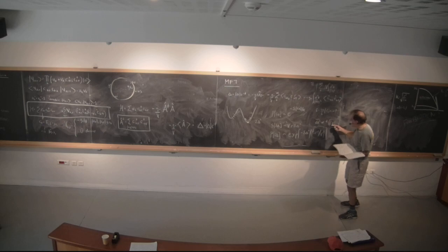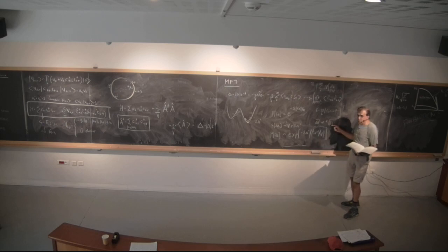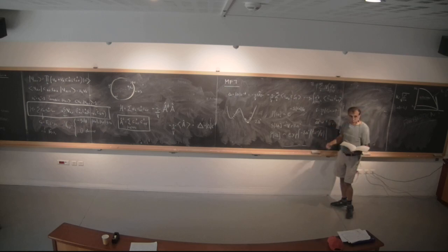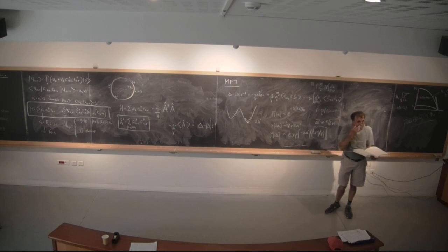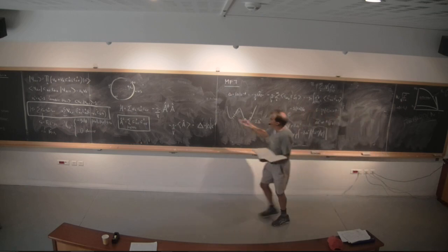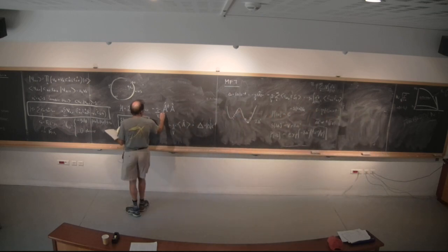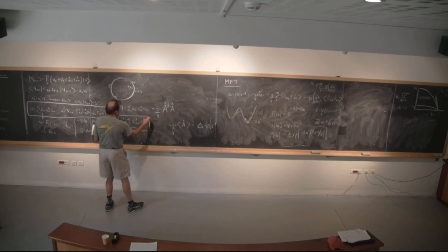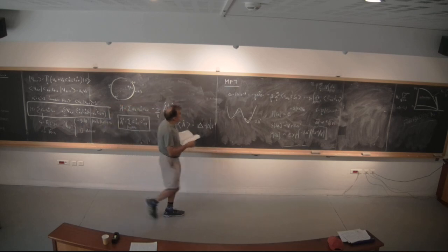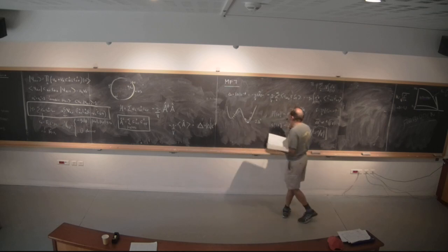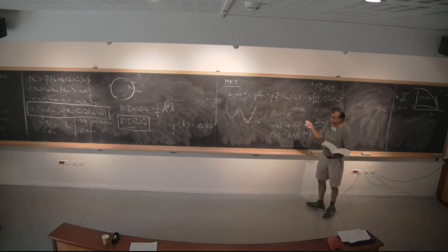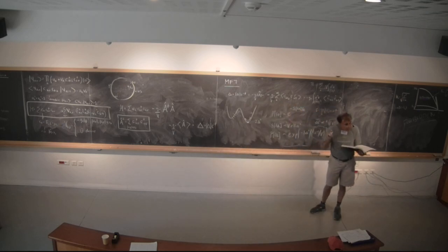And so as the volume becomes macroscopic, the size of the fluctuations becomes negligible. Since this interaction involves all k in this narrow shell, we can be sure that in the thermodynamic limit, the fluctuations in delta in this specific model vanish.